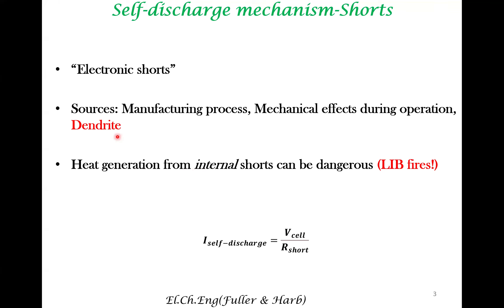The electronic current inside the battery can be fairly hazardous because heat generation from an internal short will tend to increase the temperature inside the battery, and there can be a positive feedback between the shorting mechanism and the temperature. This may lead to a snowball effect causing dangerous fires, as has been observed in lithium-ion battery fires. So this is a very important mechanism, especially in the context of wide usage of lithium-ion batteries — you really do not want to have any dendrites in a lithium-ion battery.